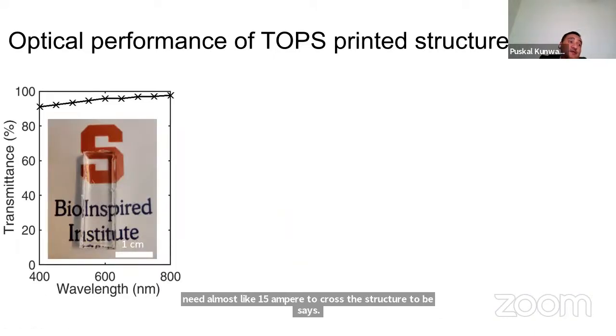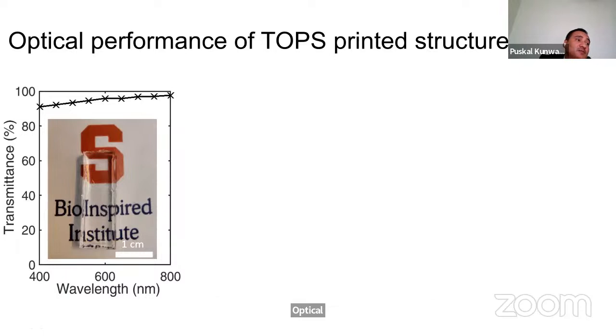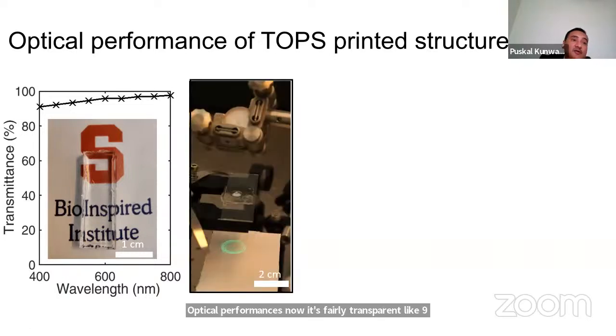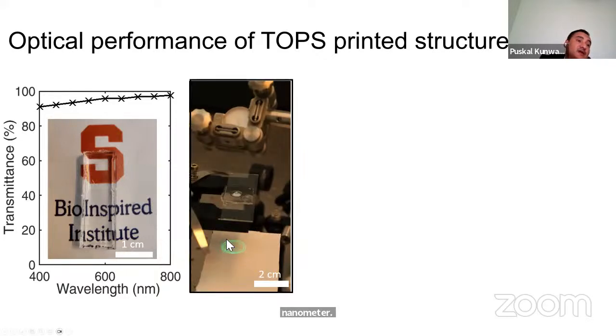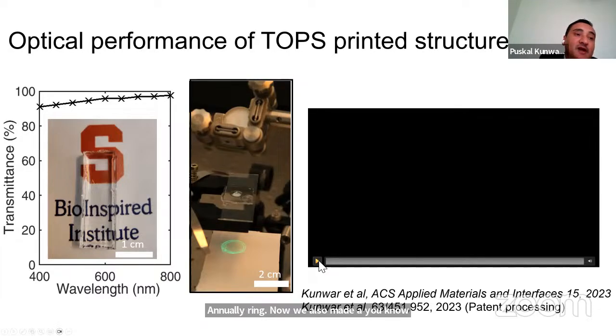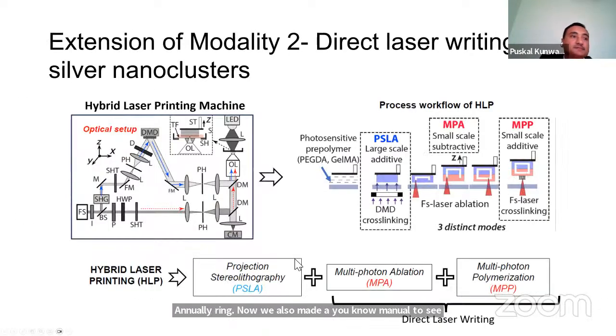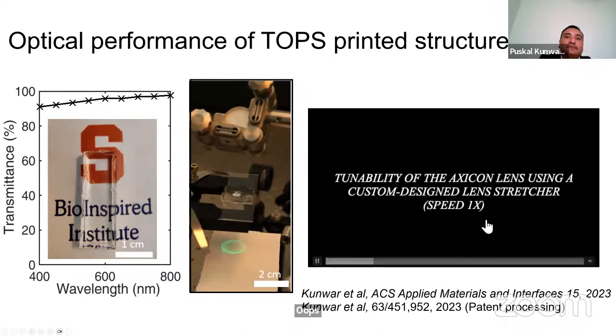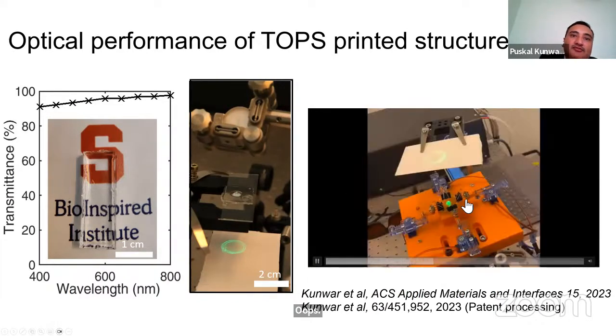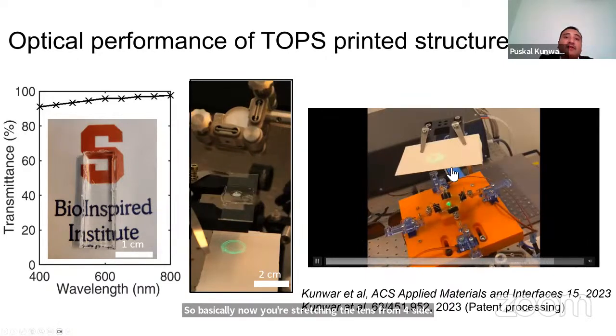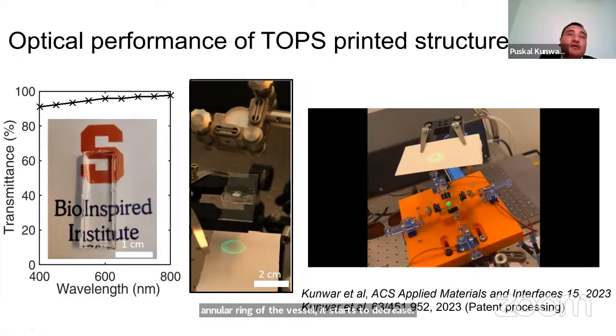Optical performance: it is fairly transparent, more than 90% in the wavelength range from 400 to 800 nanometers. We printed a axicon lens and created a Bessel beam with the help of the axicon lens, marked by this annular ring. We also made a manual stretcher to see the tunability of this lens. So now you are stretching the lens from four sides. When you stretch the lens, the annular ring of the Bessel beam starts to decrease. So we did see a proof of principle of optical components using this TOPS based printing.